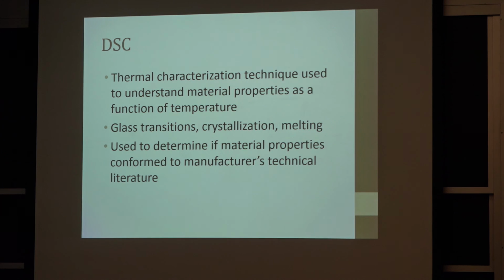DSC is a thermal characterization technique, as a function of temperature. You put your sample in there and it heats it up, and at the different temperatures where you have your phase transitions, you'll see drops in the resultant curves. So you can determine glass transitions, crystallization temperatures, and melting temperatures, and you can use this to determine if the glass you're working with conforms to what the material's cut sheet or technical literature states it should be. A lot of times we get involved after the fact, and people want to know: was the glass manufactured properly? Was it installed properly? Why did the glass break?